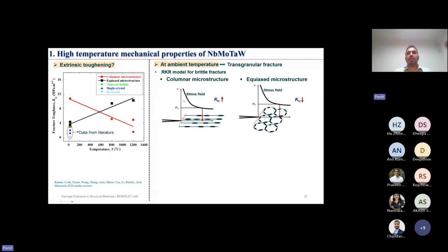So if we compare these two cases, where you have columnar microstructure and equiaxed microstructure with these grain boundary oxide particles, you can see that in the case of columnar microstructure, the probability of finding these particles, which are the microstructural weak point for this material, is less compared to equiaxed microstructures, and that could be the reason why we see such a difference in fracture resistance at room temperature.